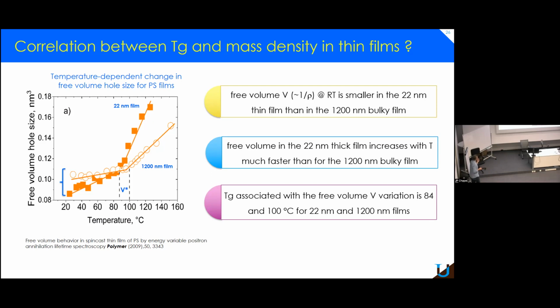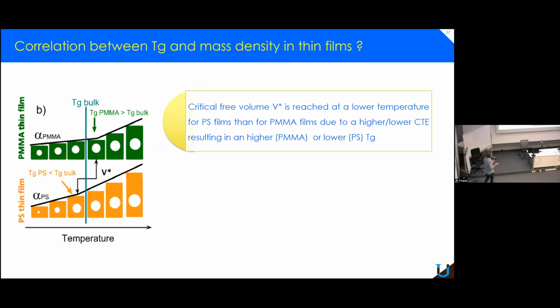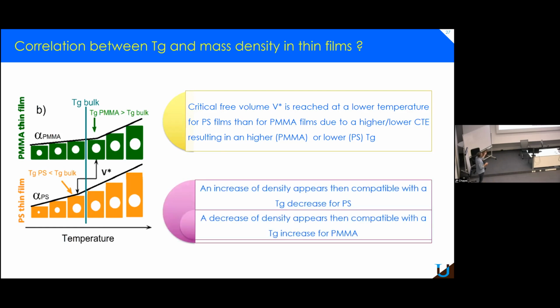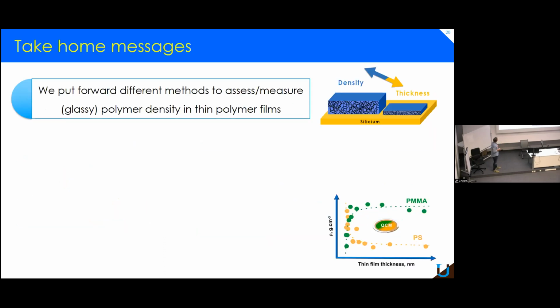So this means that the way we understand our result, especially the density result, is that the critical free volume is reached at a lower temperature for the PS film than for the PMMA film, due to a higher or lower CTE, resulting in a higher TG for PMMA or a lower TG for PS. And so you can make the two results compatible. An increase of density in PS appears then compatible with a TG decrease for the same PS. And this is also true for PMMA. A decrease of density of PMMA when you decrease the thickness appears compatible, at least to our eyes, with a TG increase for PMMA. So this is just the end.